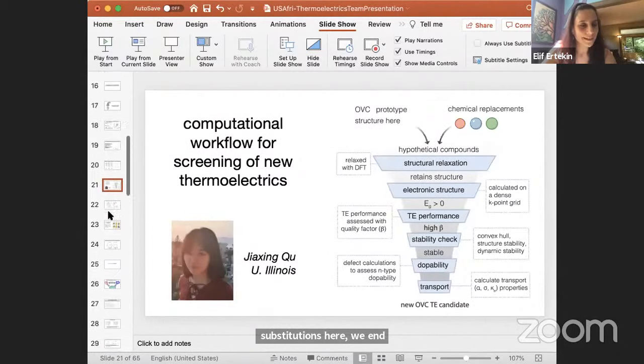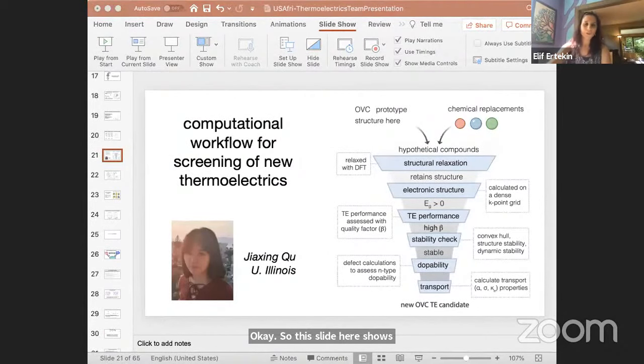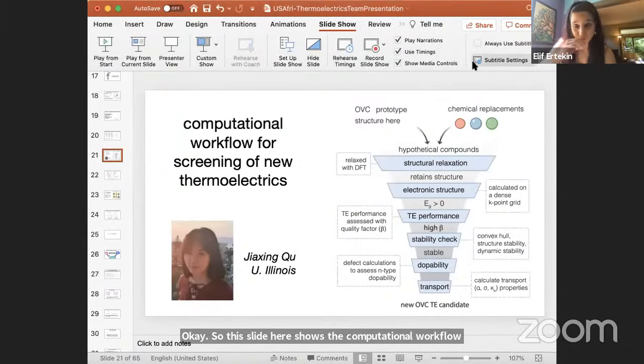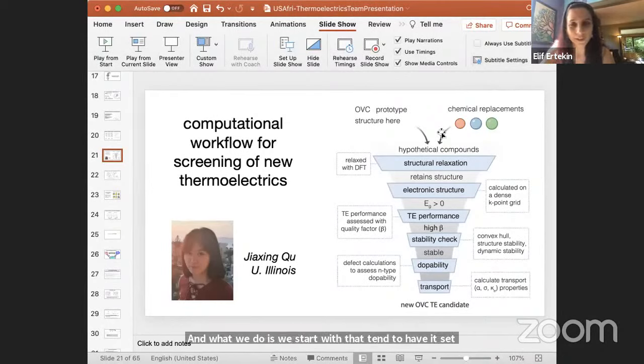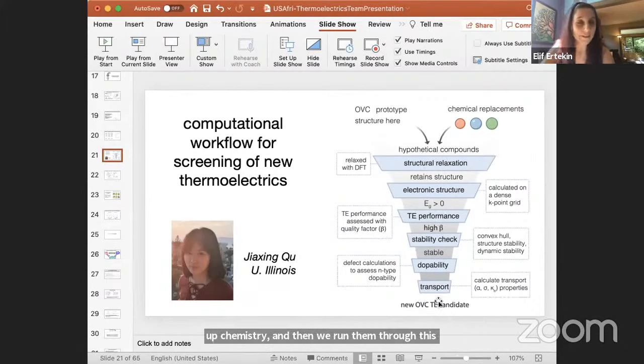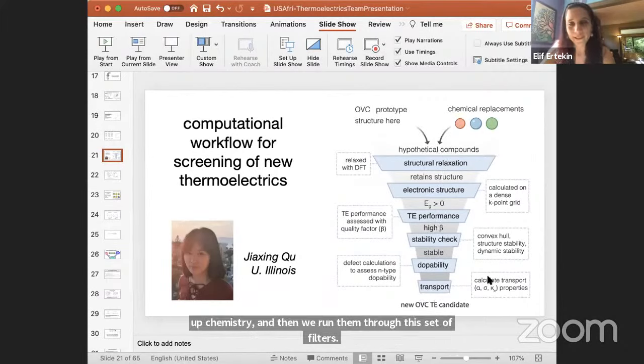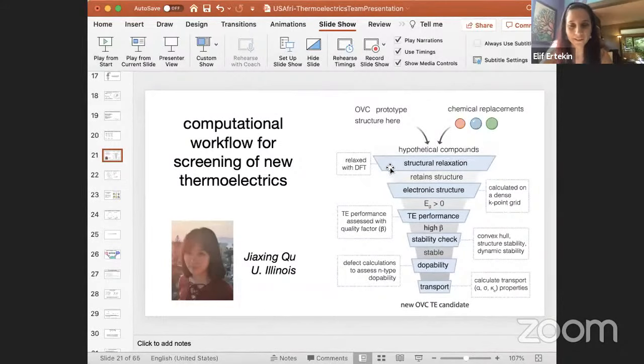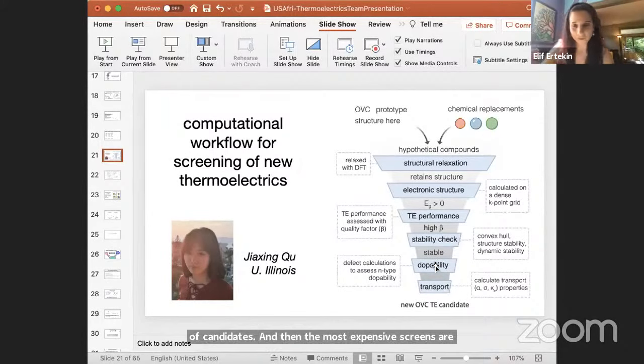Okay, so this slide shows the computational workflow that we applied. The work I'm going to show here was done by my student Jiaxing Qu here at Illinois. What we do is start with that candidate set of chemistries, and then we run them through this set of filters. The filters are applied in a strategic way, where the least computationally expensive screens are carried out first on the largest number of candidates, and then the most expensive screens are carried out towards the end when the number of candidates has already been filtered down. So in our case, the workflow starts with a structural relaxation for the compound.